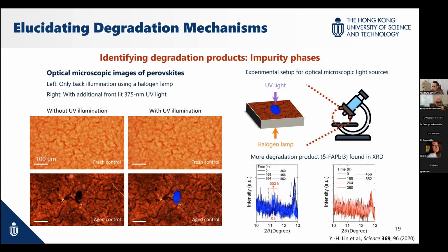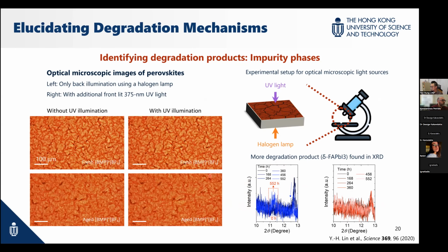But when we turn on the UV light, we see blue emitting material. But the material we are making emits around 750 nanometers. How is this material going to emit blue light? So essentially, we surveyed the entire scan spectrums. Only this delta phase FAPbI3 matches the feature of this blue light emitting material. So we believe this is the delta phase FAPbI3.